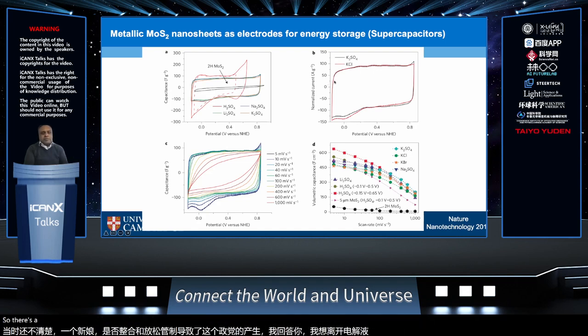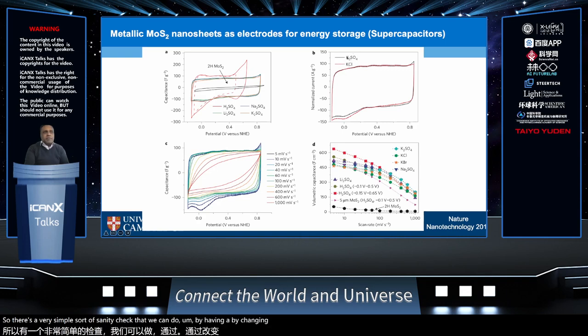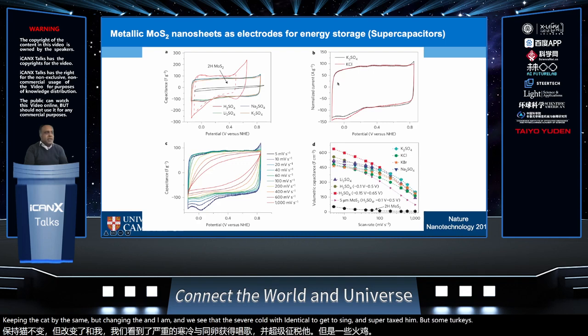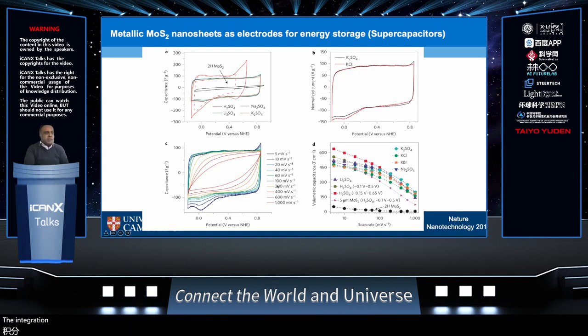There's a very simple sanity check that we can do: keeping the cation the same, but changing the anion. We see that the CV curve looks identical, suggesting it's the potassium that's intercalating and not the anion. The intercalation and deintercalation dynamics of the ions in these electrodes is quite fast and efficient.